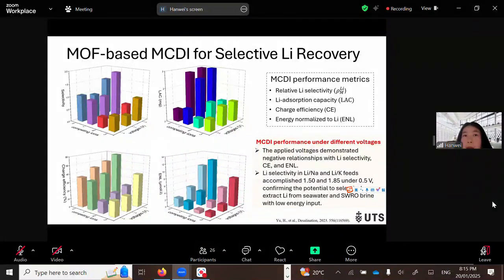We also conducted the MCDI test under different voltage, and we evaluated the MCDI performances in terms of the metrics of lithium selectivity, lithium absorption capacity, charge efficiency, and energy normalized to lithium. We found that the applied voltage demonstrates negative relationships with lithium selectivity, charge efficiency, and energy normalized to lithium. And lithium selectivity in lithium-sodium and lithium-potassium feeds achieved 1.5 and 1.85 under 0.5 volts, confirming the potential to selectively extract lithium from seawater and SWRO brine with a very low energy input.